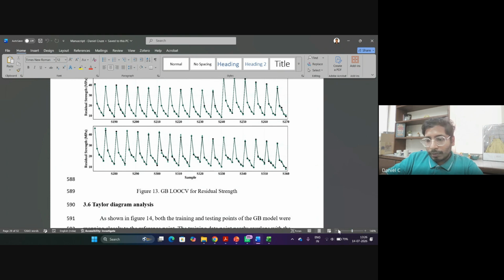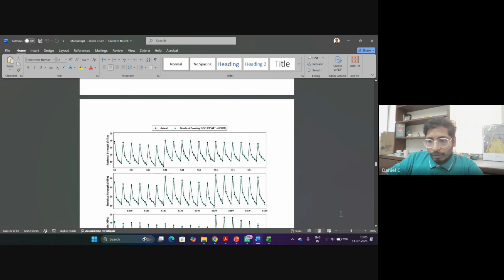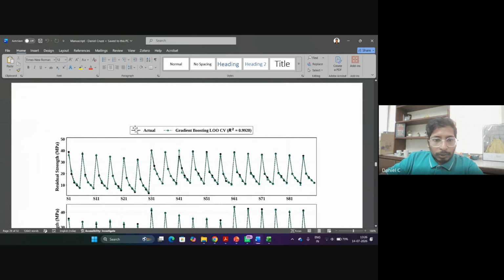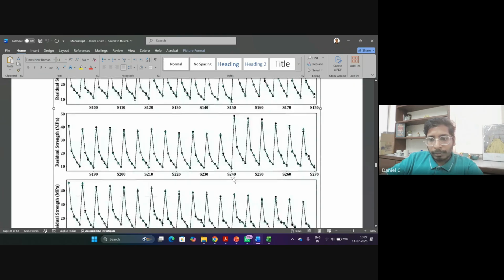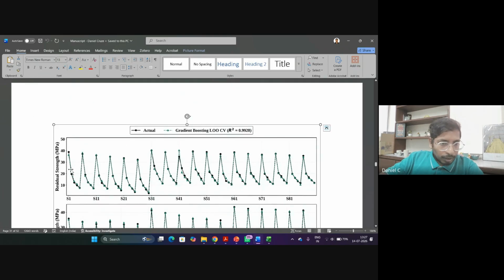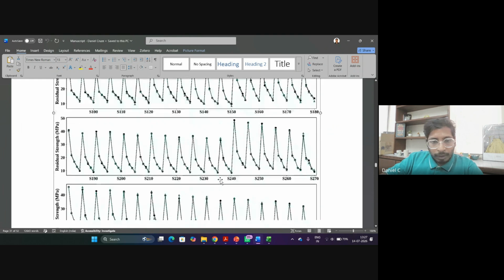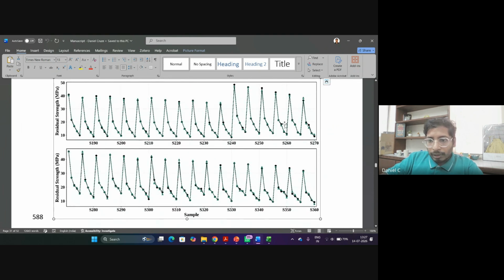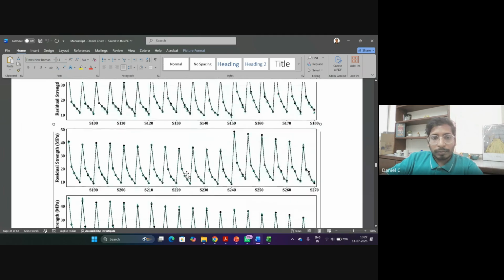See why this cross validation is very important is, you can see this graph. Actual is black color, and the green one is gradient boosting, which is 0.9928. You can see S1 is sample 1, S11 is sample 11, 21, because here the sample is many numbers, nearly 360 samples. You can see the line. In some places only you can find the results were not that close, but most of the place you can see the predicted result is very close.